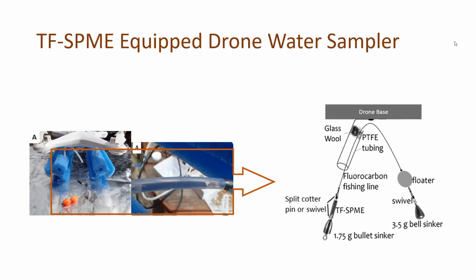The design of the thin film solid phase micro extraction drone water sampler is shown in the figures. Here the polystyrene is connected to the lower part of the drone so that the drone can float on the surface of water. There is a fishing line in the PTFE tubing. To one side of the fluorocarbon fishing line there is a floater, to which a fishing swivel is connected, and that swivel is connected to a bell sinker. This bell sinker is made of lead, and its weight is 3.5 grams.